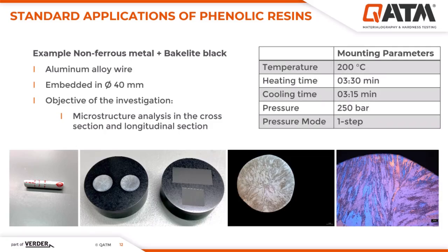Mounting was carried out with a temperature of 200 degrees, a pressure of 250 bar, and a heating time of 3.5 minutes, and a subsequent cooling time of 3 minutes and 15 seconds. Sample preparation included 2 grinding steps with SiC paper with the grit size of 600 and 1200, 2 polishing steps with 3 micron and 1 micron, and the final polishing step with Epoxyl F. To see the microstructure, either a sodium hydroxide solution or an electrolytic Barker etching was used. Both methods enabled a reliable microstructure analysis.